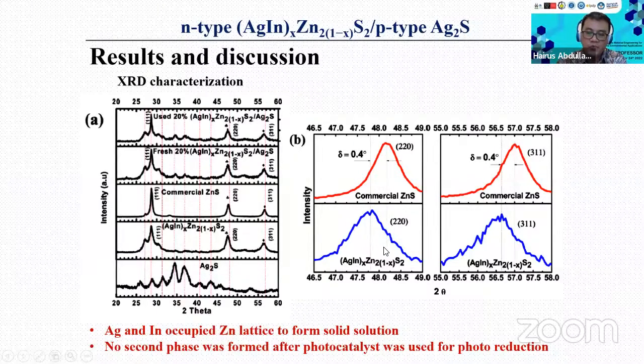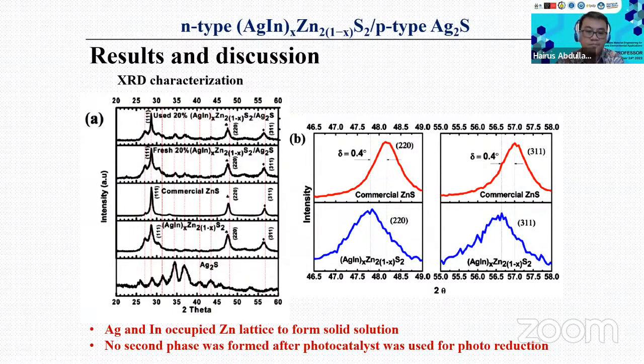So we try to zoom in on a very specific area of this peak, right, at 220. So you see the peak shifts to the right-hand side for the pure ZnS, commercial ZnS, while our material, after doping with the AgIn, the peak shifts, right? So it means there's a lattice parameter change because of the AgIn doping into the lattice.